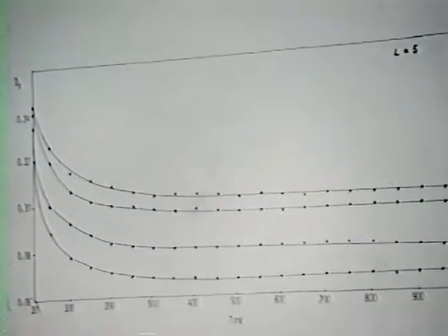The same thing here. Here is diffusivity versus time for various sizes and so on. So if you want to make exact observations from our simulation, we make the following observation. If the molecules are relatively large, their effective diffusivity appears to vary with time, which is what I just told you, even after relatively long time. And even for a small molecule, we find that they still vary with time, but much more slowly.